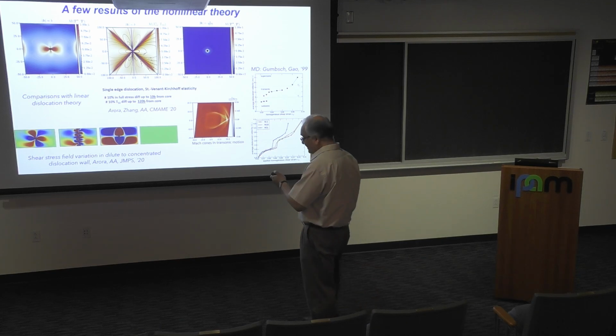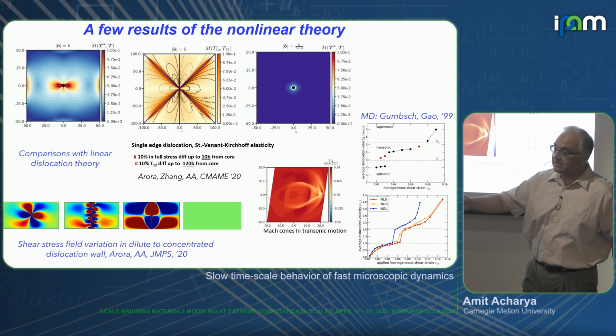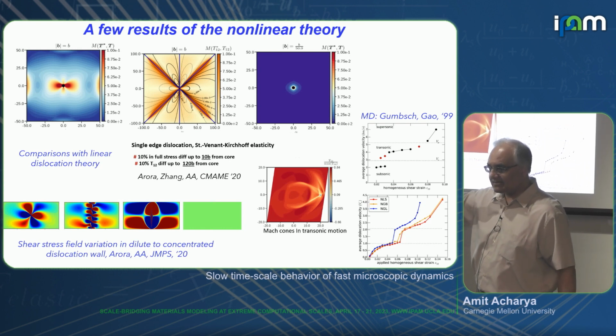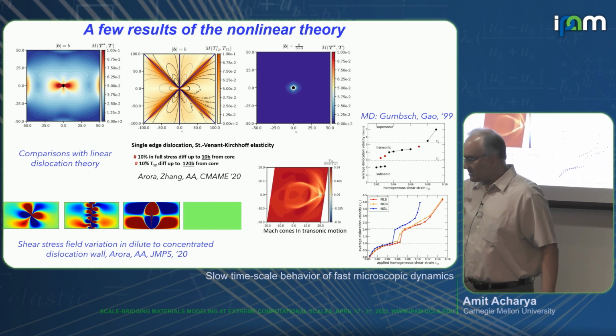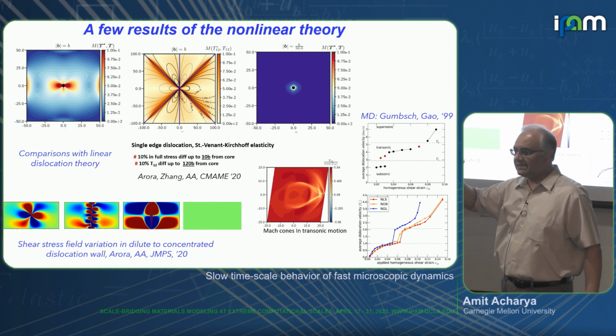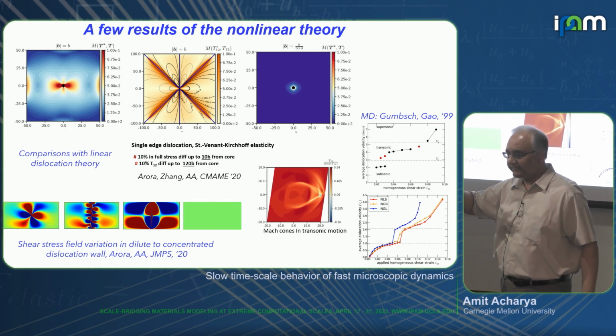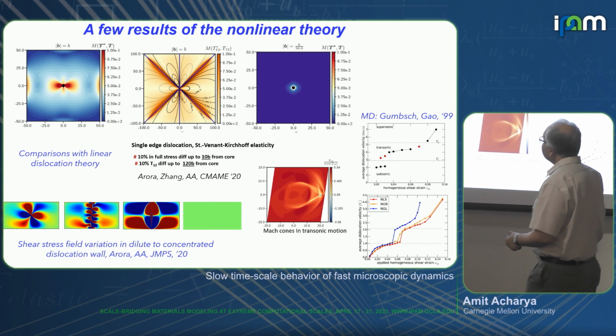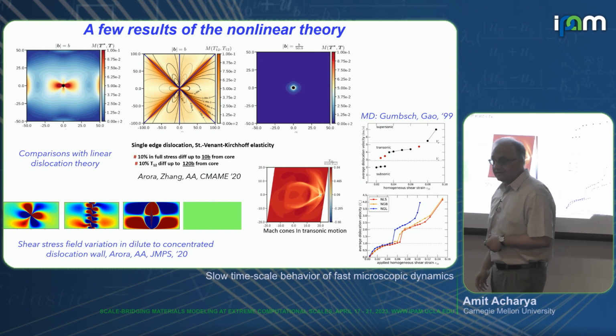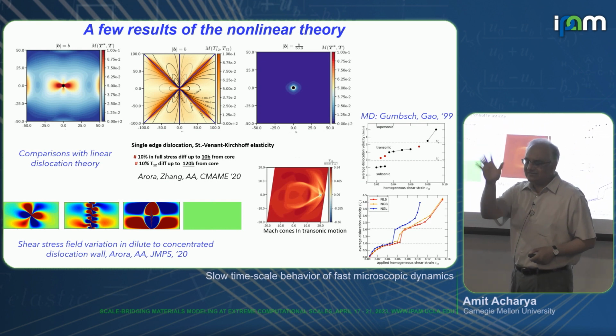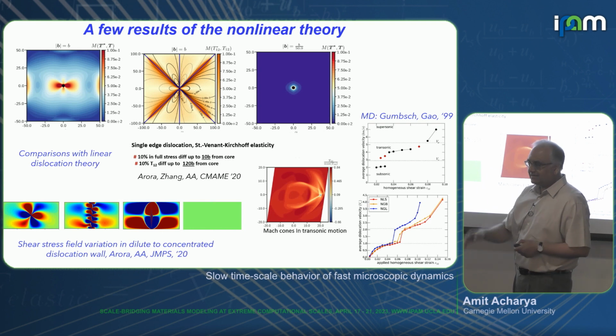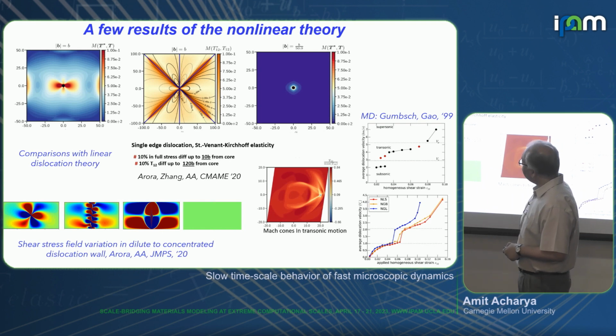And so very quickly, some results here. I need to speed up here. This is the advertisement part, right? So, okay, so you compute. This is a fully nonlinear theory, okay? So now one thing you want to do is calculate nonlinear elastic fields for dislocations. So here it is, and then you compare. Everyone will tell you, no, outside the core, nothing matters. I mean, the linear elastic field is good enough. Well, it depends on your definition of good enough.